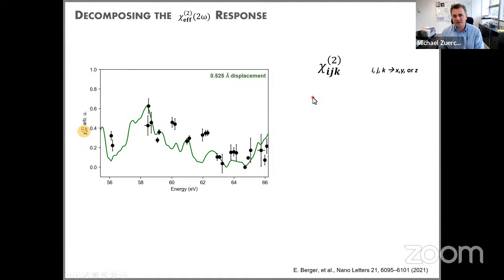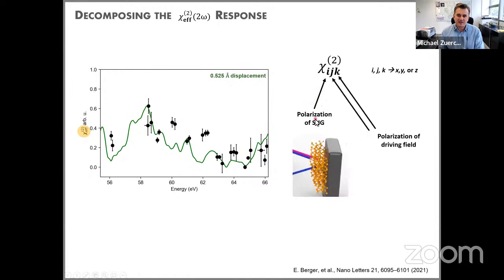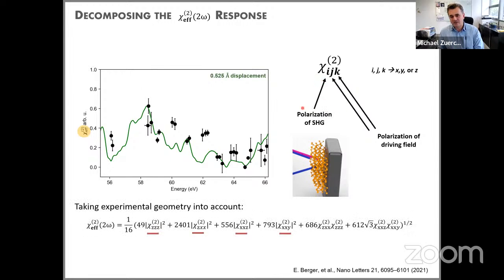So if we have a rank 3 tensor, with tensor elements I, J, K, we can think of those as X, Y, Z really in the crystal plane. The way you think of this is that the coordinate I is basically the polarization of the SHG, and then the polarizations of the two electric fields that cause the second harmonic are J and K. So you think of it like you have two electric fields corresponding to J and K that drive the system, and then the second harmonic response, the second order response, would be I, right? So this is how we can think of the designation of the tensor elements.